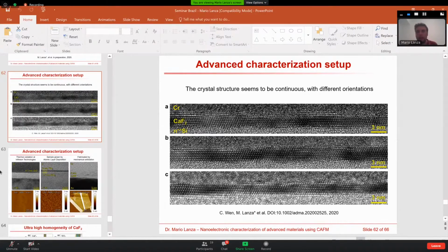I have to say that we have studied calcium fluoride because calcium fluoride grown by molecular beam epitaxy can form a quasi-van der Waals structure. It means the surface of the calcium fluoride is terminated with fluorine atoms and they don't have dangling bonds. So the interface between molybdenum disulfide, for example, and calcium fluoride can be very clean. For this reason, we are considering this material for 2D electronics. And this is the main point: the calcium fluoride is grown by molecular beam epitaxy.